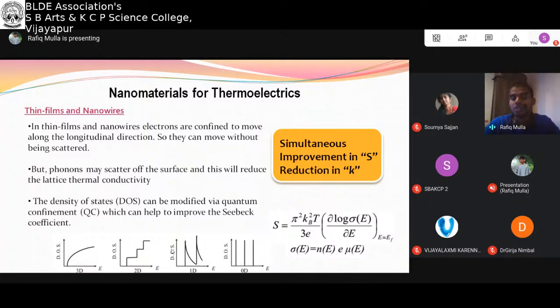By having this kind of drastic change in the density of states, we can improve the Seebeck coefficient. So by going from bulk to thin film or nanowires, we can see changes in the Seebeck coefficient. The Seebeck coefficient is defined with this expression, where it has a relation with the derivative of the energy dependent conductivity. That conductivity is N e mu. So N of E is the energy dependent concentration, that is nothing but the density of states. So by tuning the density of states, we are tuning sigma, and the drastic change means a drastic value of this parameter.